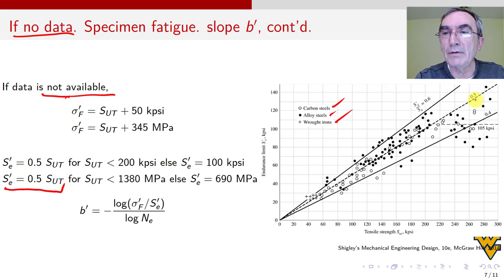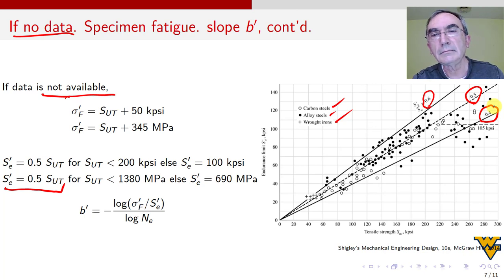Well, it could be 0.5, which is this line. It kind of goes through the middle of all the data, so yeah, okay. But if you look at the other data, you draw this line, and that's 0.6, and that's 20%. And then if you go down here, that's 0.4. That's 20% in the other direction. So there is a plus or minus 20% error there on that coefficient alone, okay?